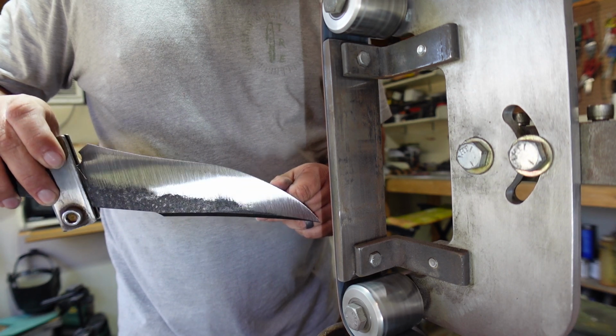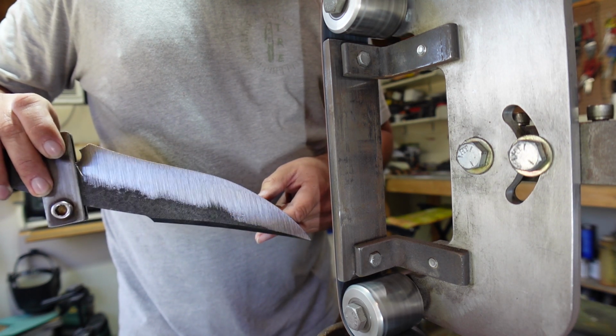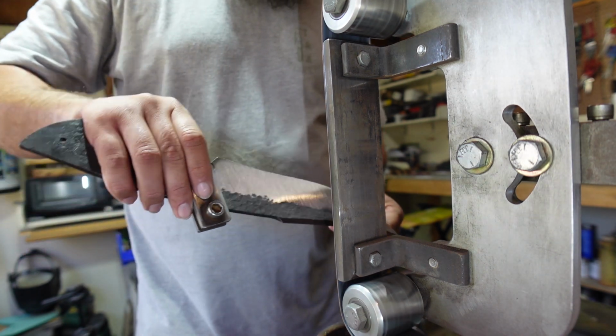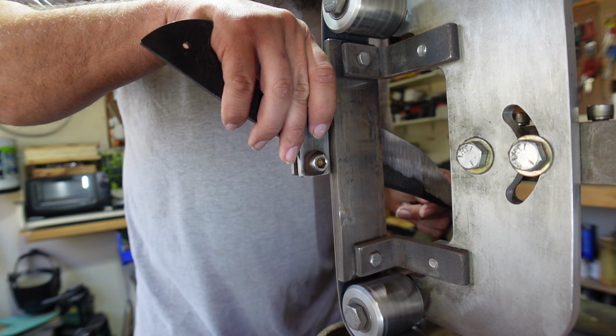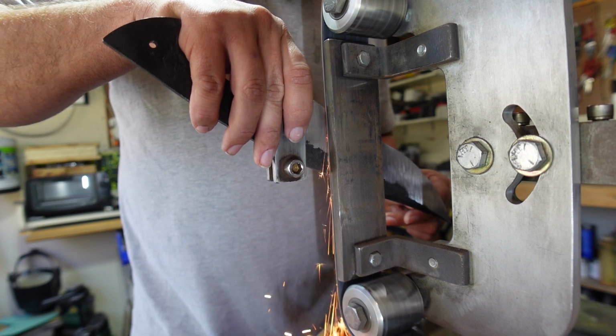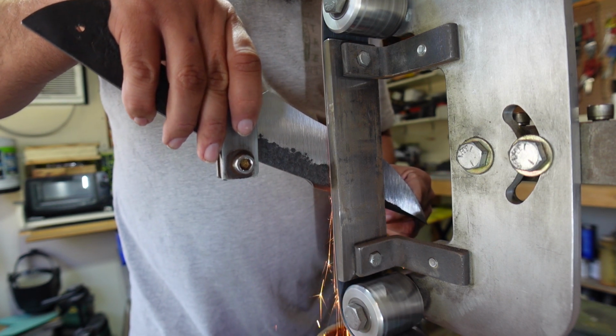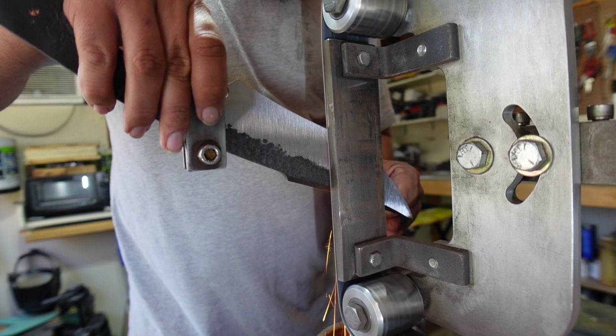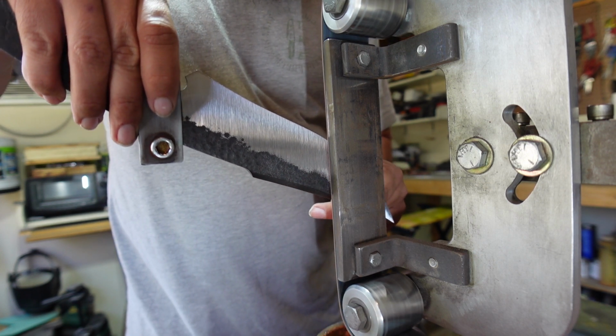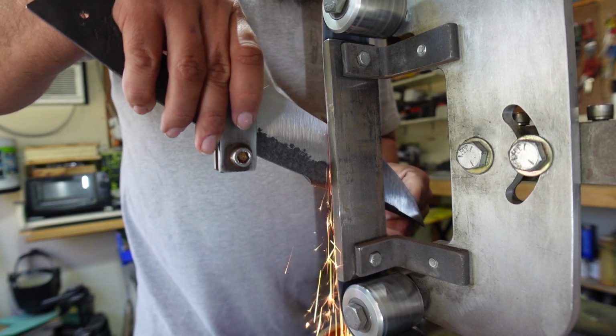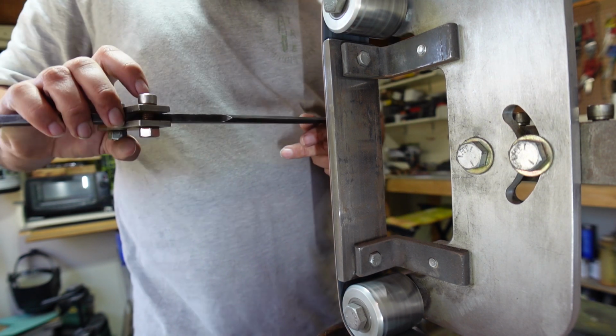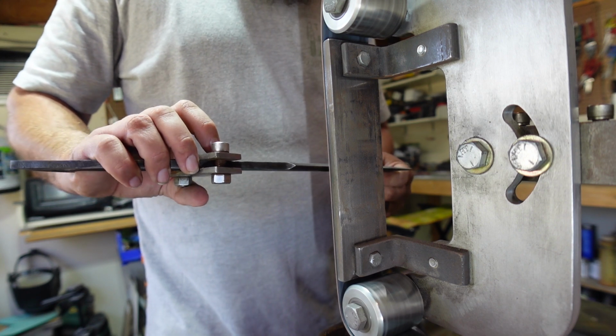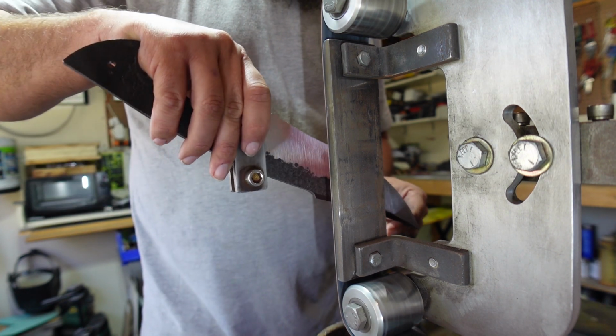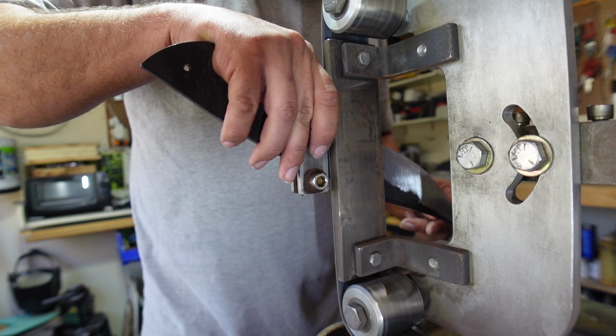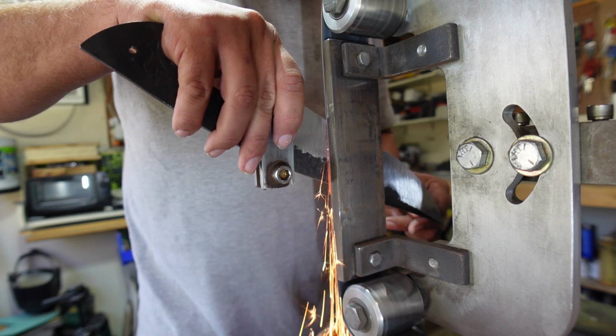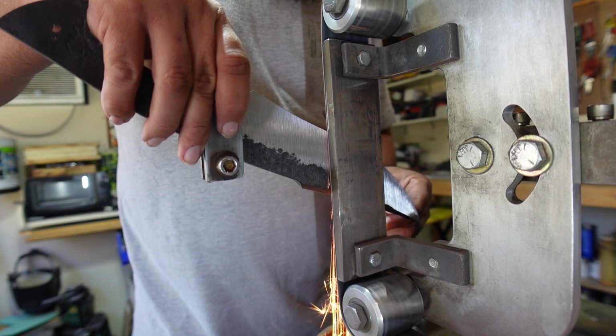So once we got the decarb layer ground off, we went back after it with a brand new 36 grit belt and started evening out those grind lines, which are going to create the striations once we do our acid etch and sanding process. That gives us a really cool texture on the bevels. You want to make sure that when you're doing this step that you're taking your time. You're not really pushing the blade into it. You're letting the belt do its job and grind nice and evenly across the bevels.